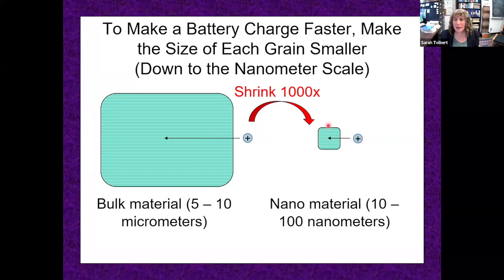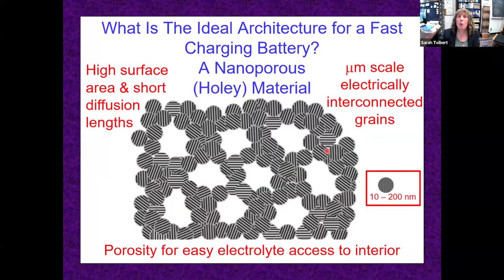The problem is if you have little individual nanometer-sized pieces of battery material, it's very hard to move electricity into those materials, and you need to move lithium and an electron into the material at the same time. So to solve that, we make nanoporous or holey battery materials. The idea is we make little building blocks with short diffusion lengths for our lithium ions, and then we have holes that are full of our liquid electrolyte, where the lithium ions can zoom through the holes and make it to all of the reactive sites in our little pieces of active material. Importantly, the entire material is electrically interconnected so that the electrons can get out of the material.